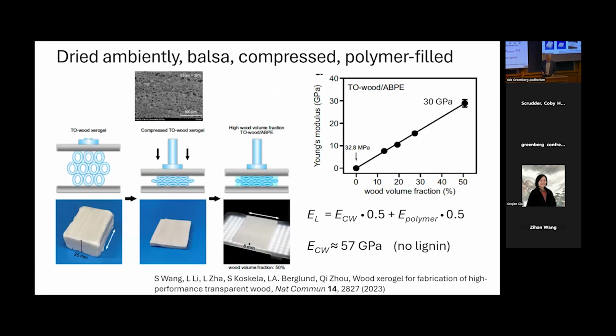And this is the last example, where we have a composite, and the composite is prepared by first preparing a so-called xerogel. It means that we can dry it under room temperature, ambient conditions, and we generate a highly porous material, which we compress and fill with a polymer. And these are the modulus data for different wood contents. If we use a similar, very simple theoretical approach, we end up again with a cell wall modulus of around 60 gigapascal. So that seems to be reachable.